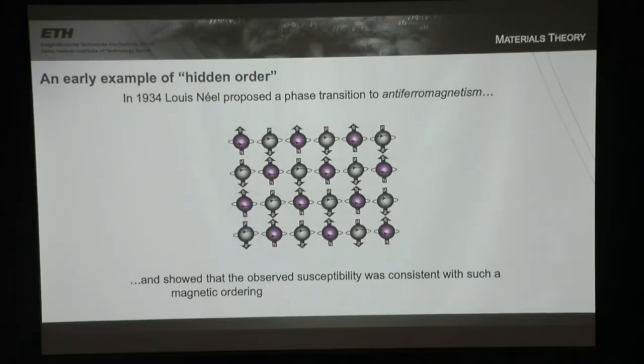And Néel went one step further than that. He showed theoretically that the form of the magnetic susceptibility is consistent with such an antiferromagnetic ordering. So he had an explanation, a theory that was consistent with what was observed, but still, I'd say the order was still hidden. It was post-dicted, if you like, by the development of this nice theory, but there was still not a direct measurement. Everything made sense, but there was no direct measurement of the antiferromagnetic order.